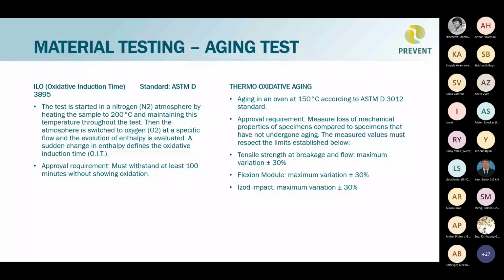There is the oxidative induction time. This is a test where it starts with a nitrogen atmosphere and you heat it to 200 degrees C and you maintain the temperature along the test for a certain period of time. Then you switch the atmosphere to oxygen and you see the evolution of the enthalpy of the material over time. And then there is a specification to meet. Approval requirement: it must withstand at least 100 minutes without showing oxidation. So that's the requirement. It should not oxidate for 100 minutes.